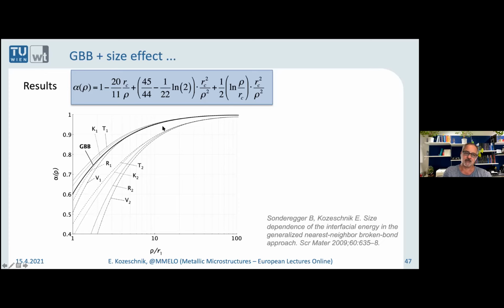You can see that once the particle becomes smaller, the effect becomes incredibly large for the interface energy. Because keep in mind, the interface energy is cubed in the nucleation barrier, and it's in the exponent of the nucleation rate expression. So the factor here, like 20–30%, doesn't sound very spectacular, but you cube it and then you put it in the exponent, and then you have tremendous impact. So this is the size effect. It becomes very strong once the nucleus becomes smaller.